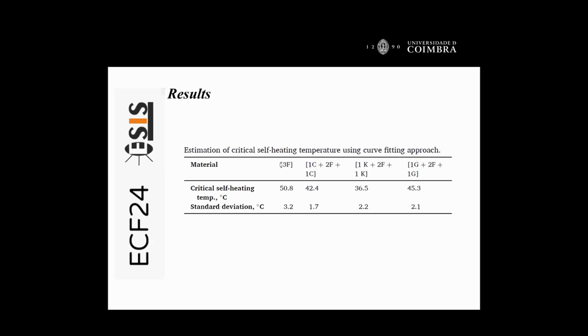For example, only for flax, the temperature is around 51 degrees. But when we analyze in terms of hybrids, the temperature decreases, and it depends on the materials that are involved. For example, for carbon flax, we have around 42.4 degrees. For Kevlar and flax fibers, we have 36.5 degrees. And for glass combined with flax fibers, we have 45.3.